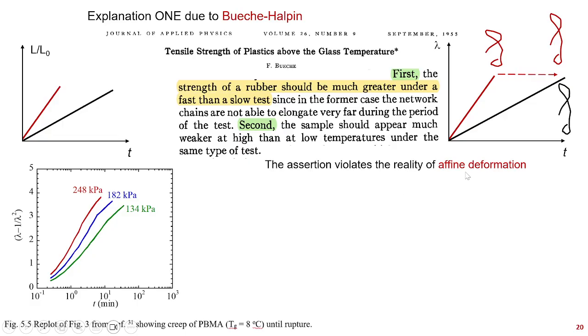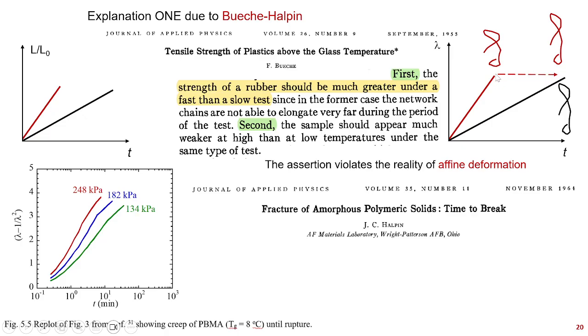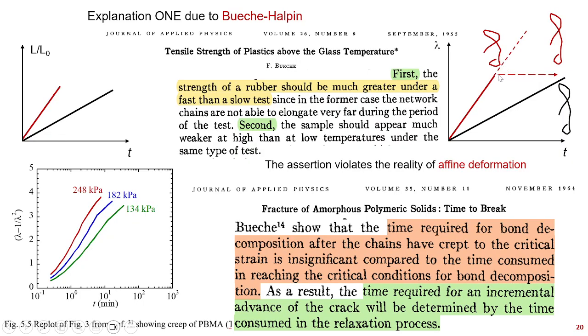So therefore you can essentially avoid being broken, because at that time sufficient stretching hasn't occurred yet. So this is his explanation, that the higher rate will be stronger because when you use a higher rate, which is red relative to the black, you haven't spent enough time, and therefore the chain hasn't stretched. And this goes with further papers saying that, which is the key mistake we accepted for 70 years, that your rubber is spending most of the time reaching the critical molecular strain and spends very little time when you reach the critical strain for chain scission to occur. That's the claim.